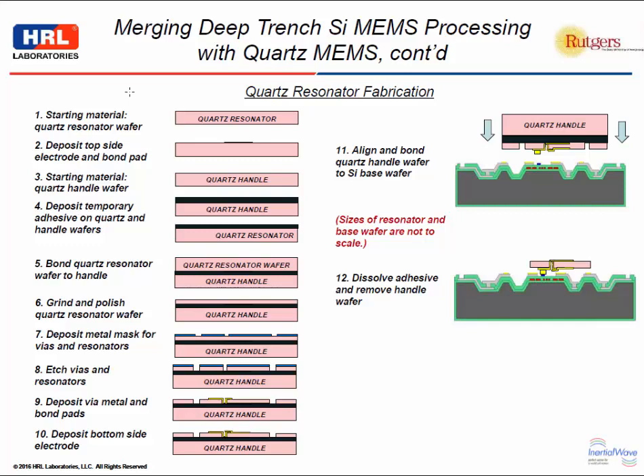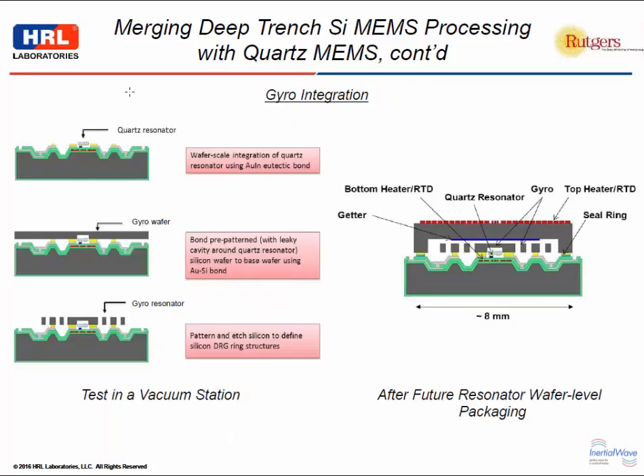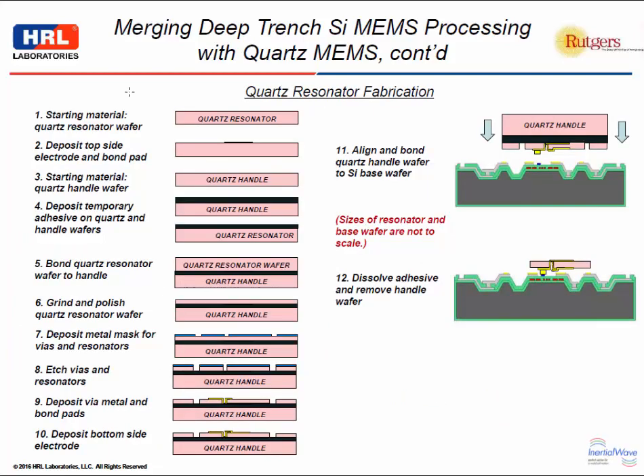So we decided to put the quartz down first and then follow up with the silicon processing. The quartz processing is, if you followed our VHF processing in the past, similar with a few modifications. We start out now with both a quartz handle wafer and a quartz resonator layer. We bond those now with an adhesive bond instead of a fusion bond. This is a wax bond that we bake at about 150 degrees C. We thin the quartz. This is now an SC-cut quartz wafer, not an AT-cut quartz wafer. We grind and polish it down, CMP polish it, and deposit our metal mask for doing the via and the resonator etch at the same time. Then we apply the via metal and bond pad metal, and finally the bottom electrode metal.